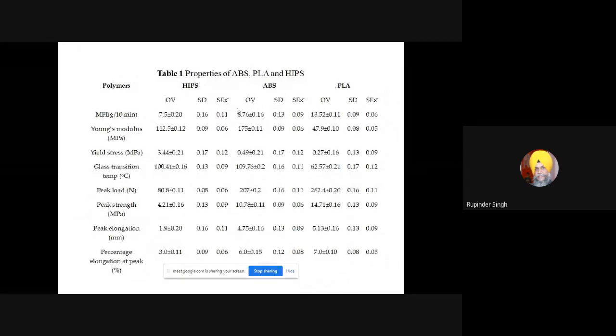So in this particular example, to make our point, we selected three different materials. One is ABS, another was PLA, and the third was HIPS. These three materials were selected because they have a significant difference in their properties. You can see in this table, the MFI of the HIPS as the observed value was 7.5, whereas for the selected grade of ABS, it was 8.7, and for PLA, it was 13.52. You can see the flow properties are significantly different.